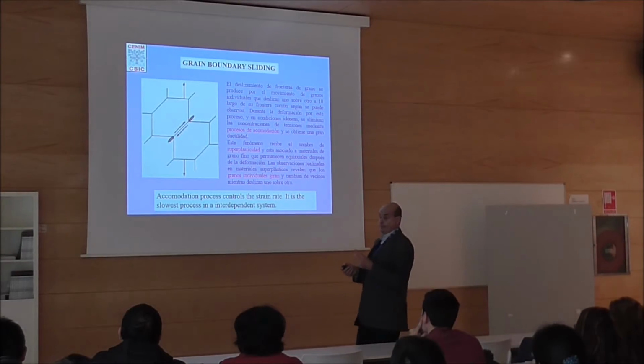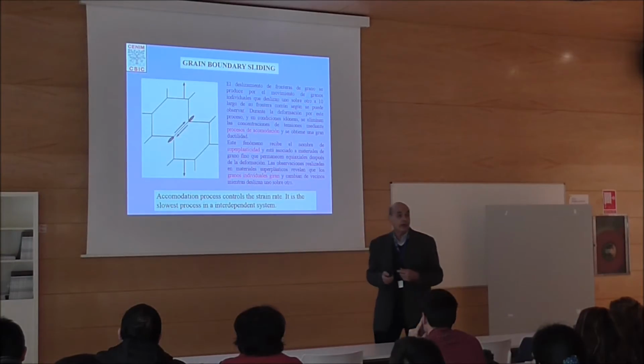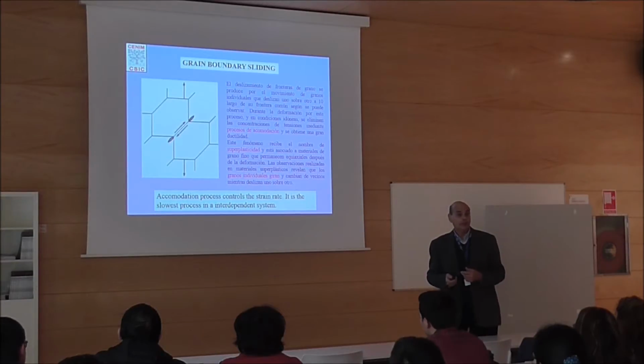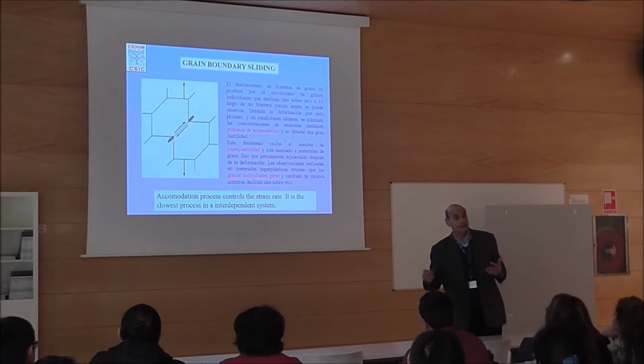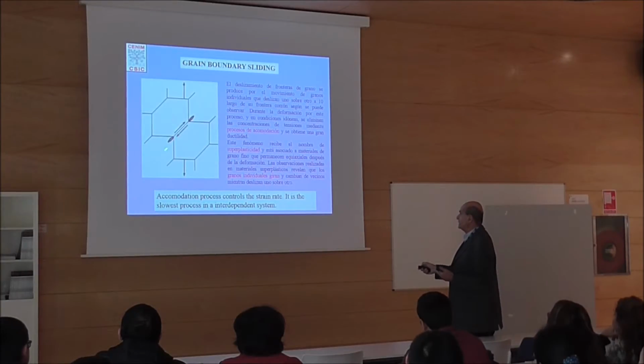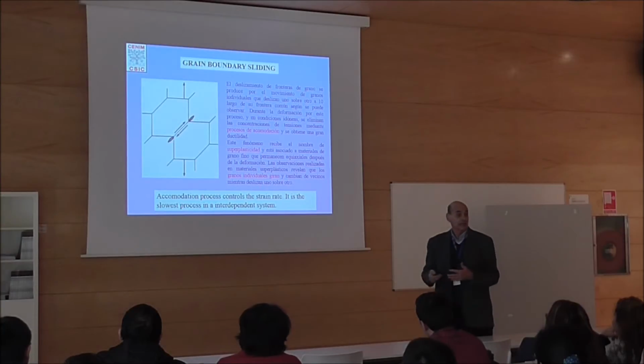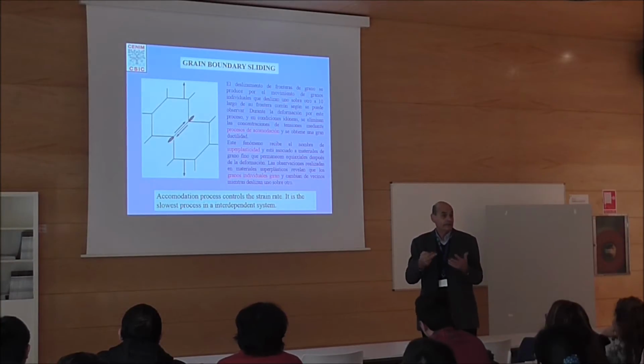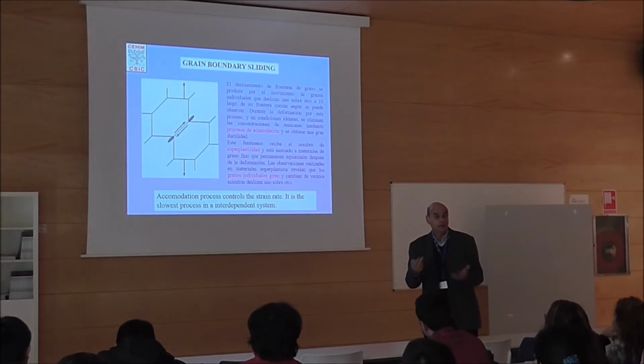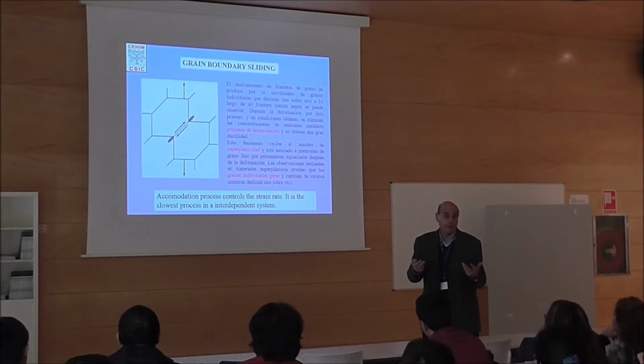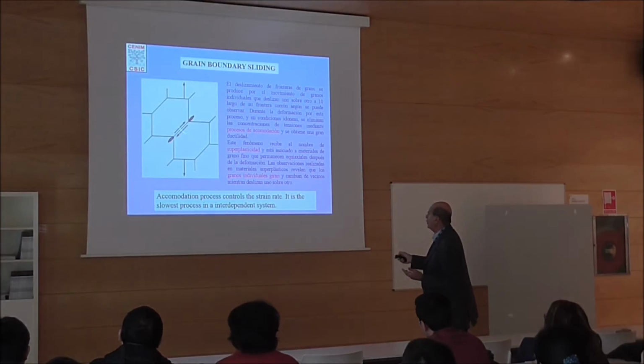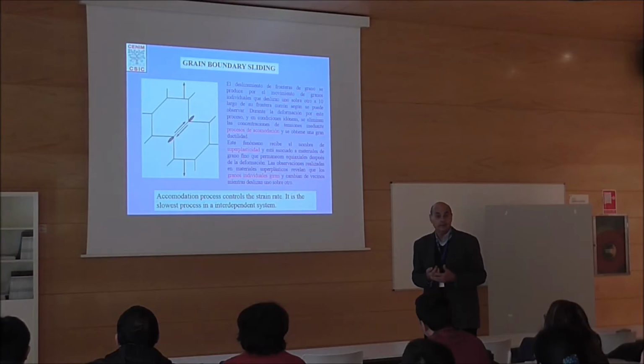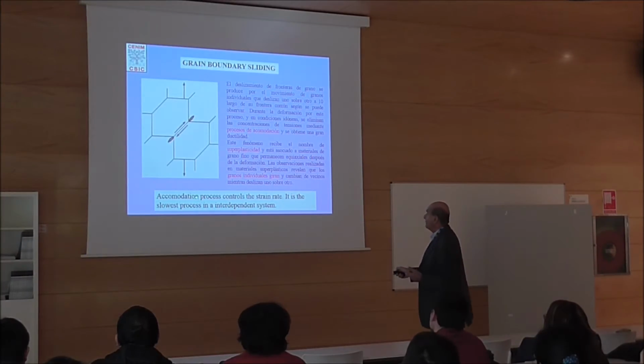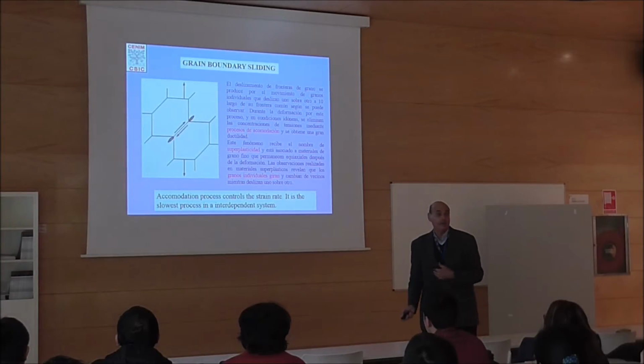And again, here we have two processes, and this is one question that I got. Superplasticity has to be explained by grain boundary sliding. Grain boundary sliding means that these boundaries slide on each other. But you can imagine when this boundary slides over here, you will have some cavities and some stresses, and very bad things will happen. If you don't close this, it will rupture. So we will have no superplasticity, but just a mess. So we have to close this, and how do we think it closes these holes, these cavities? By an accommodation process that controls the strain rate because it is slowest.